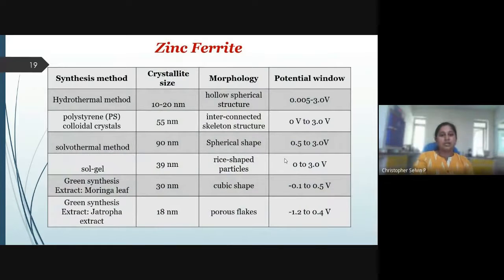So this is a comparative table which describes the different performances of the zinc ferrite material prepared by different modes of synthesis. Almost we can say significant variation in the crystallite size and different morphology also. And the material exhibits capacity, intercalation deintercalation behavior in the different voltage window, depending on the electrochemical setup employed for testing that material.